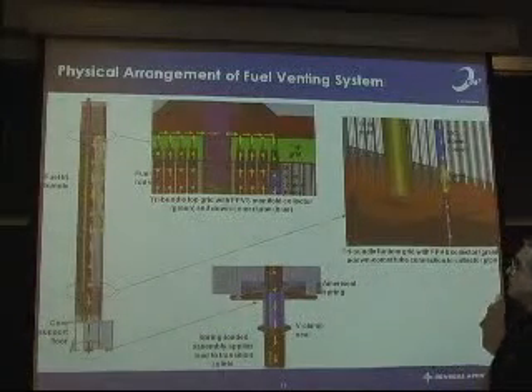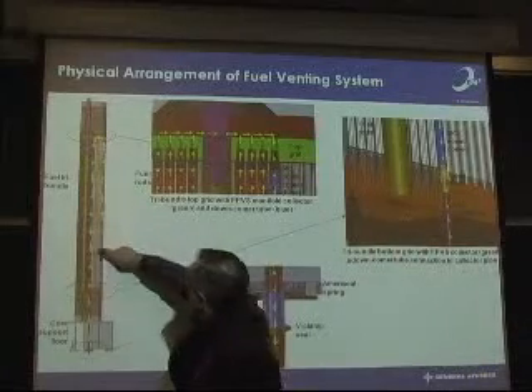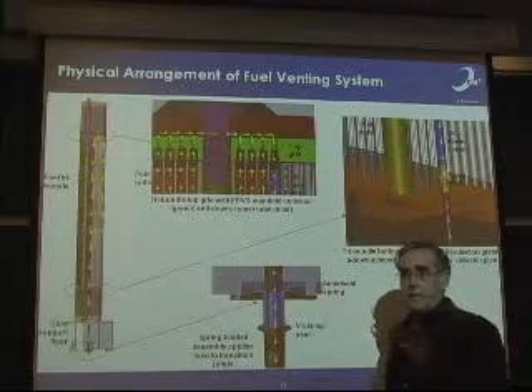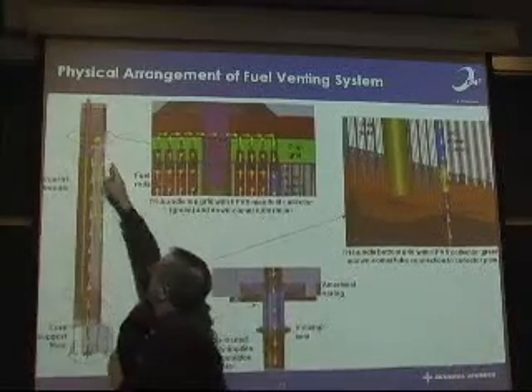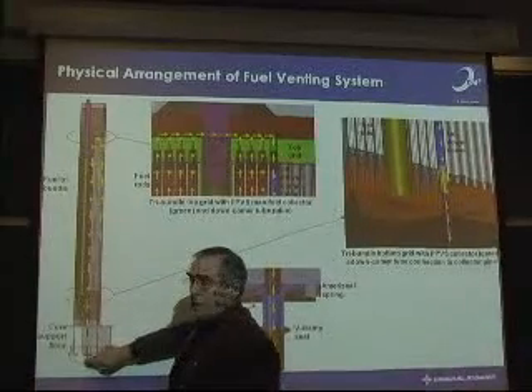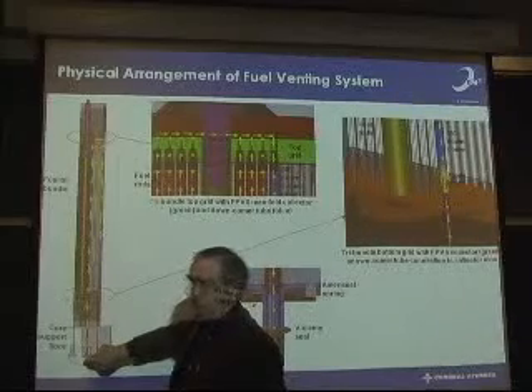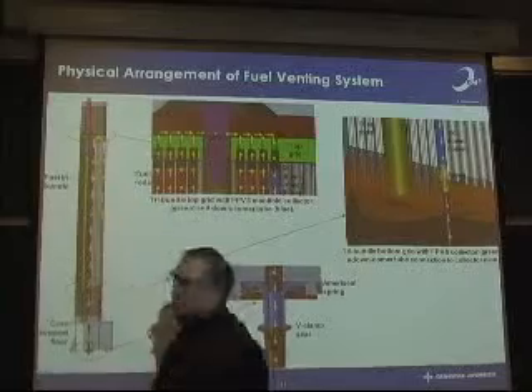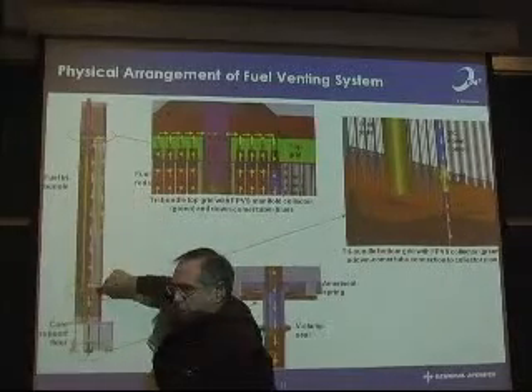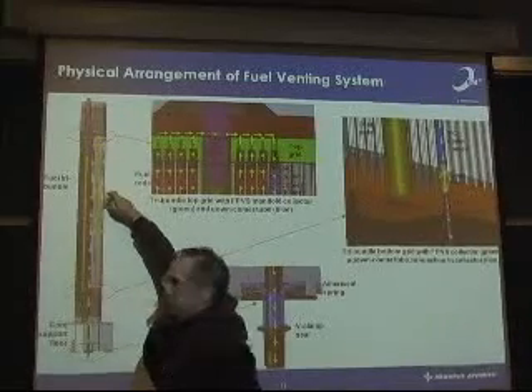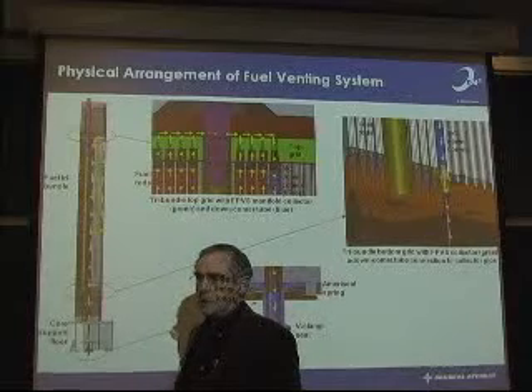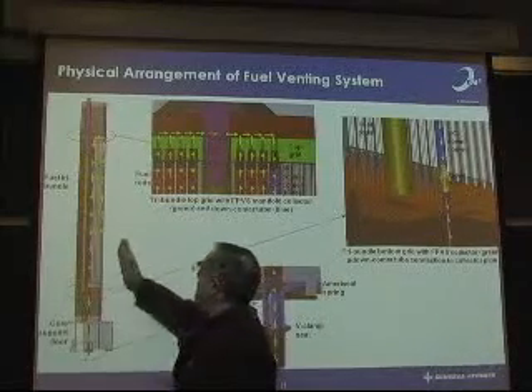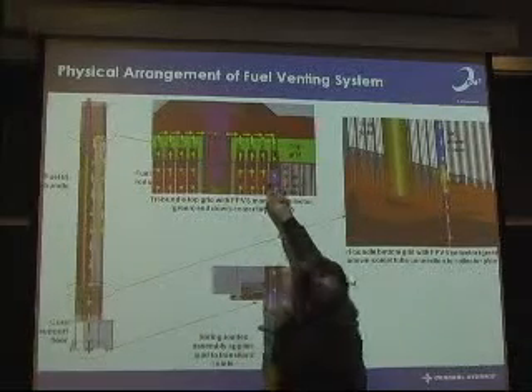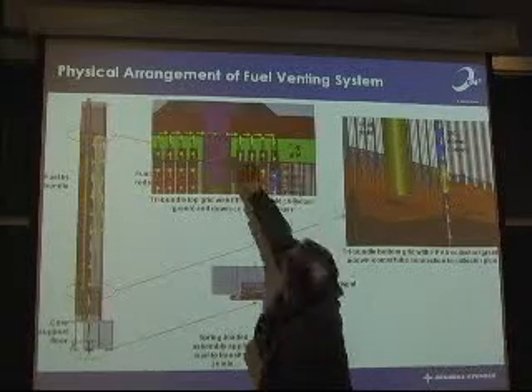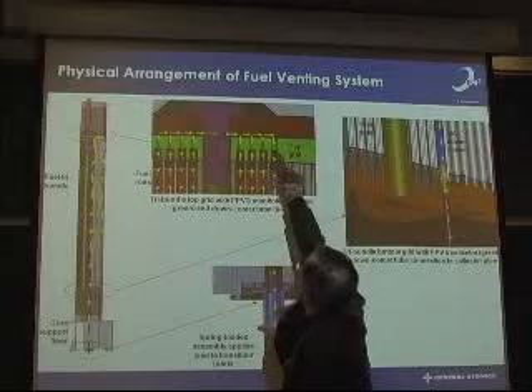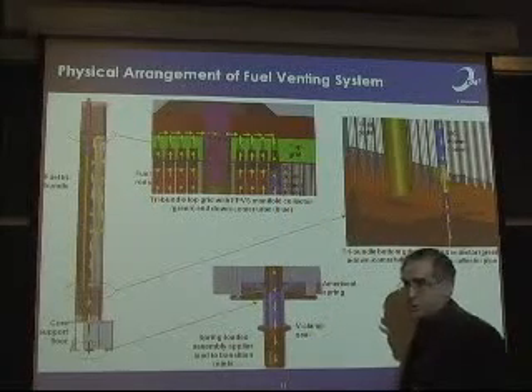On this particular design, this shows the fuel rods. The fuel is actually an annular pellet. The fission gases travel up, turn around, and then come down a central downcomer, and then connect to a distribution network at the bottom, in the cold bottom of the core. We spent about 2 weeks trying to decide whether we need to vent up or down, and we decided we had to vent in the upward direction because if debris fell down, we wanted to be sure that we didn't block the pathway of the gas. And so we decided to vent up. It turns around in a manifold at the top, in that pressed silicon carbide manifold, and then vents in the downward direction. So that's the vent design.